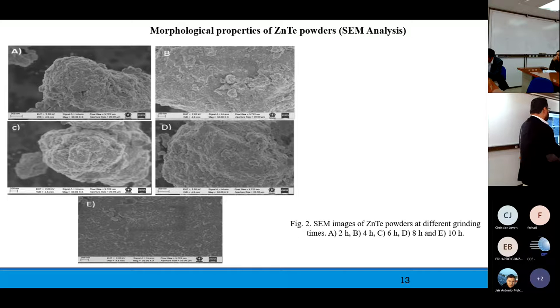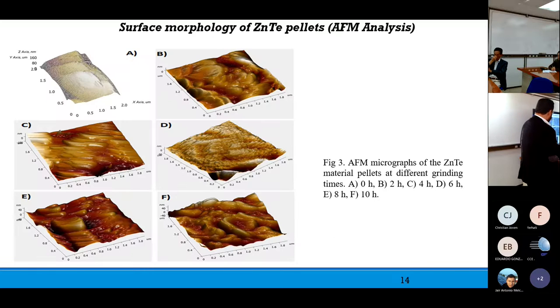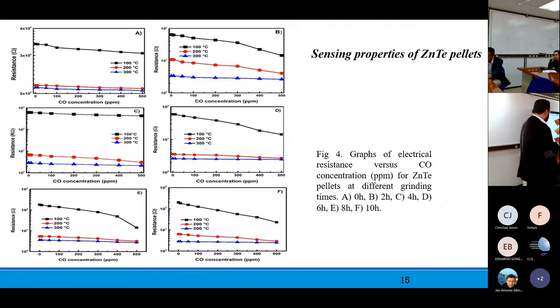We study the morphological properties of the zinc telluride powders by SEM analysis, and in all the cases, the materials present conglomerate particles, which can be caused by the high energy of the milling processes. We study the surface morphology of the zinc telluride pellets with atomic force microscopy, and we saw that all the pellets have an irregular grain size, and the roughness of the samples increased with the milling process.